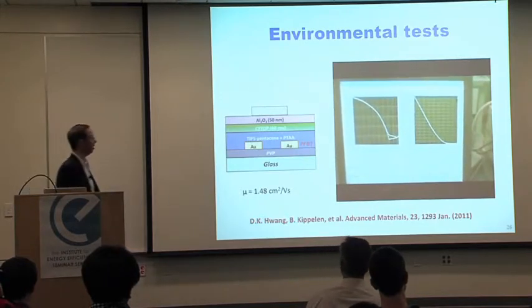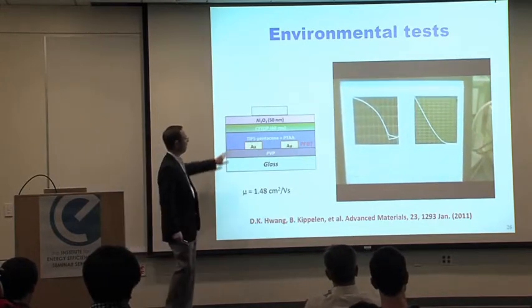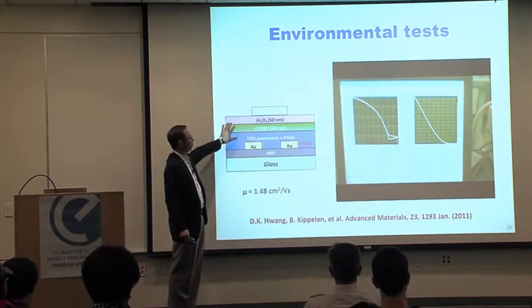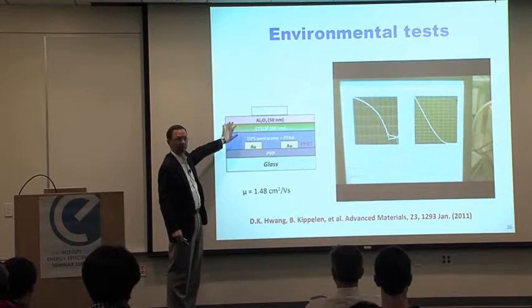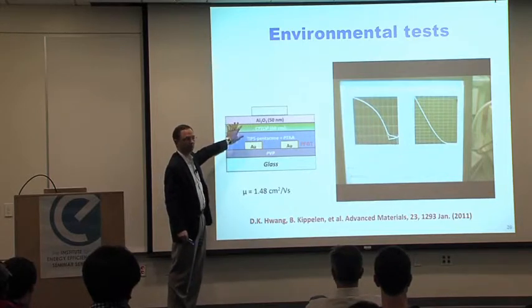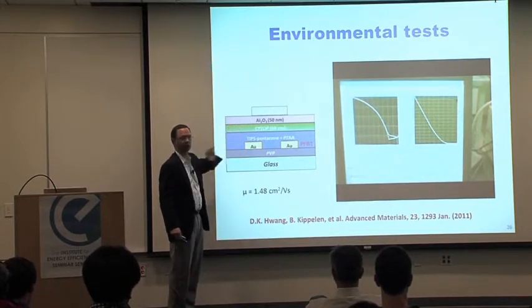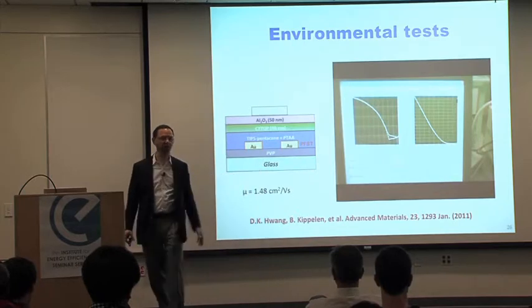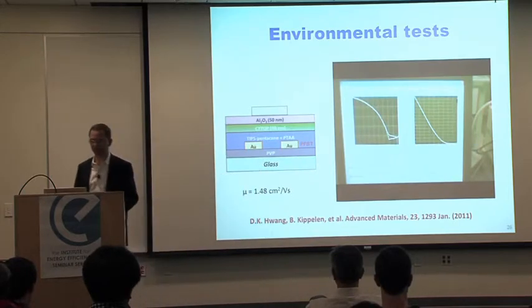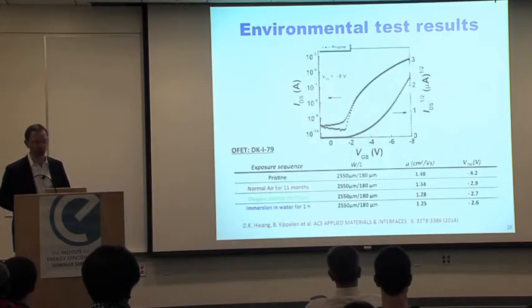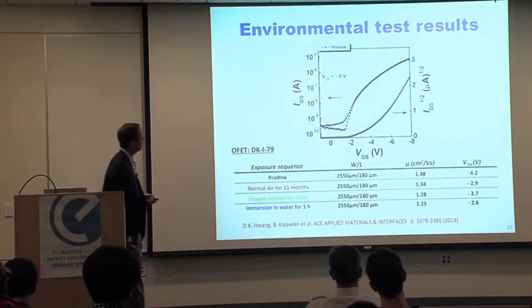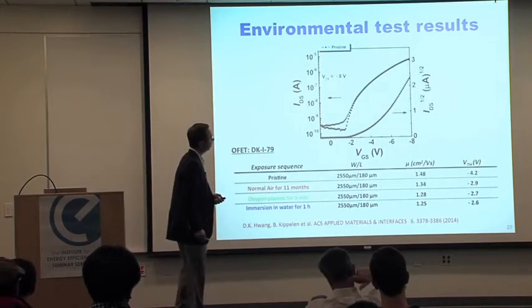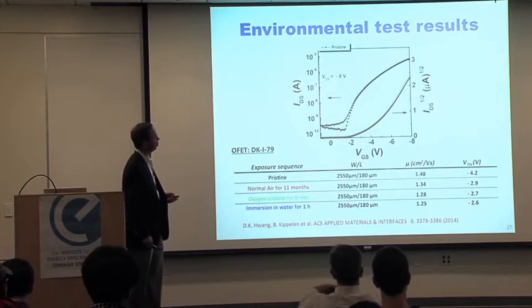Now, I should mention that, of course, he's also made reference or test structures where he had only CYTOP as the gate dielectric or only aluminum oxide grown by ALD. These devices, after you put them in a plasma chamber, they're done. Nothing works anymore, okay?